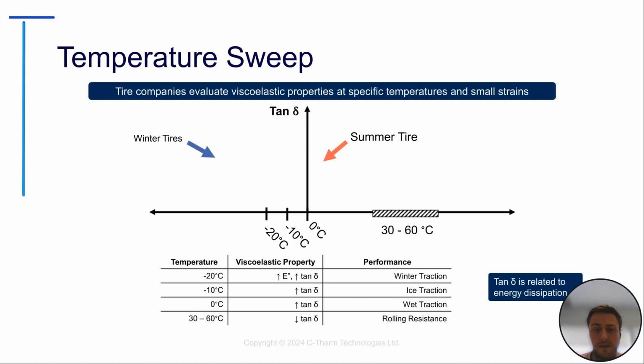So at -20 degrees Celsius, a higher tan delta usually suggests better winter traction. At -10 degrees Celsius, a higher tan delta will suggest better ice traction. And then at 0 degrees Celsius, a higher tan delta will suggest better wet traction. And then finally, at elevated temperatures such as 30 to 60 degrees Celsius, a lower tan delta will suggest better rolling resistance or mileage. This is really dependent on what your internal study is doing. Every company is a little bit different, but these are good ballpark values to follow.